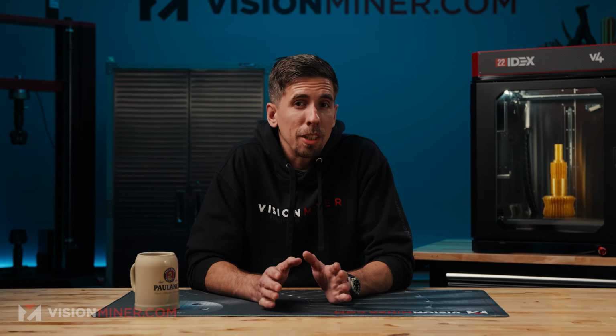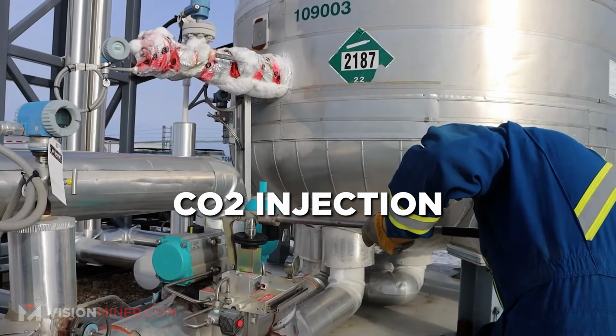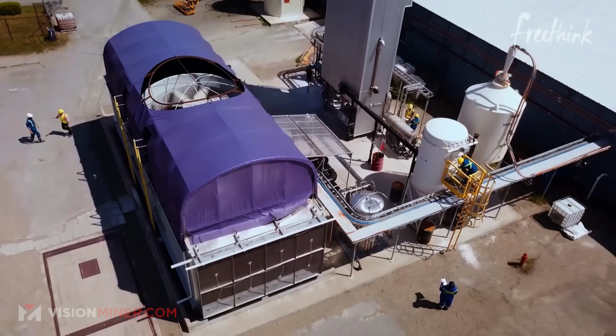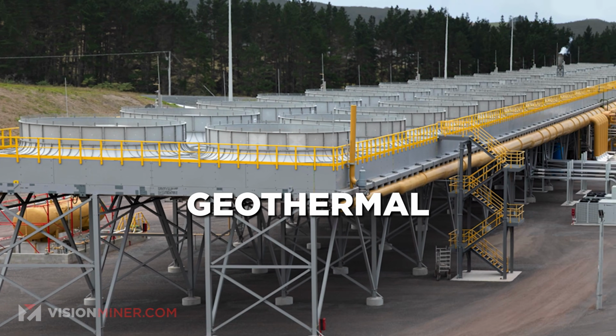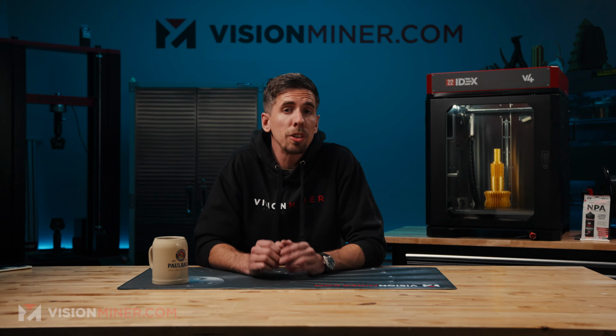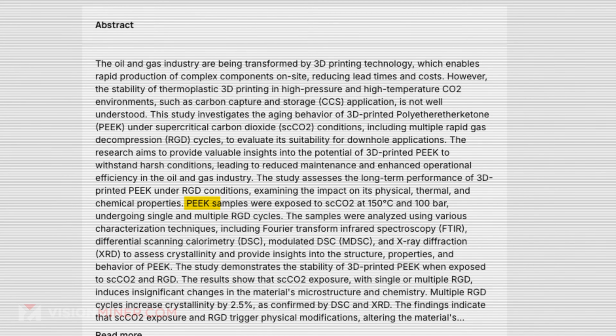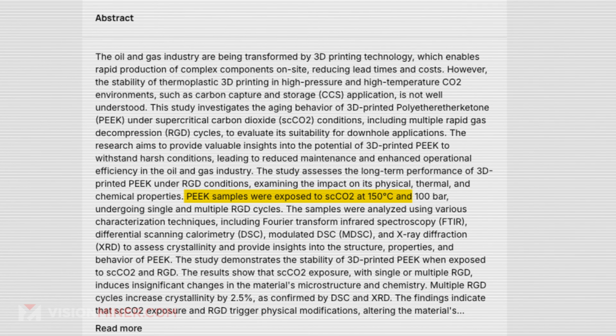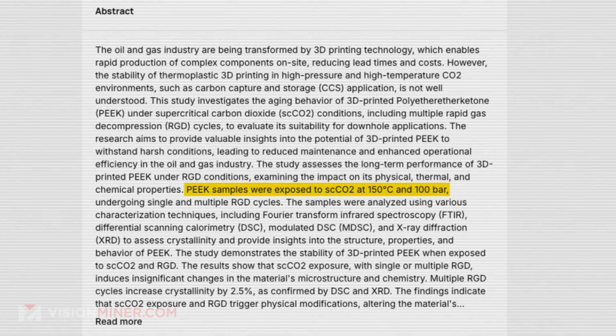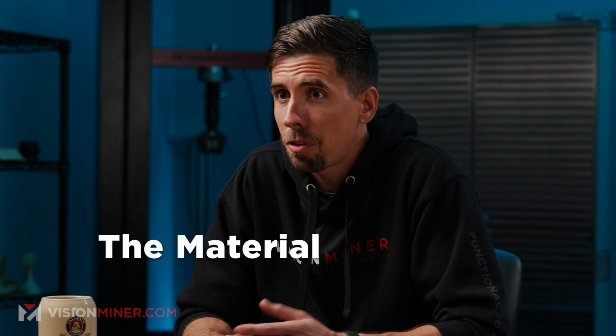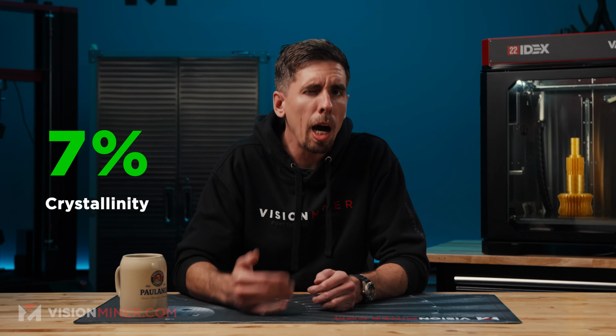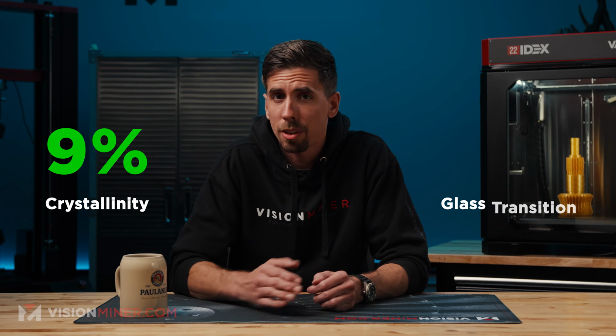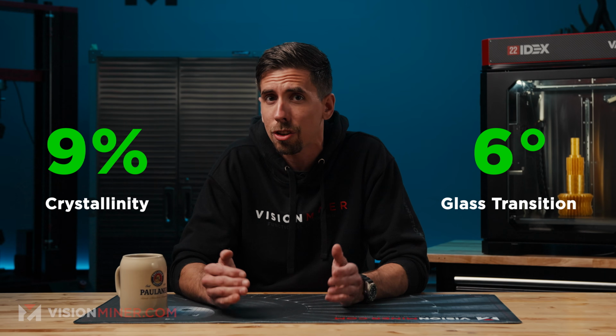And the surface area is growing. CO2 injection for enhanced oil recovery, carbon capture for storage, geothermal, hydrogen valves. Valland is already printing those on the same equipment. Researchers at KAUST ran 3D printed PEEK through supercritical CO2 at 150 Celsius and 100 bar, which is about 1450 psi, with repeated rapid gas decompression cycles. The material survived. Crystallinity went up about 9%. Glass transition shifted up about 6 degrees.